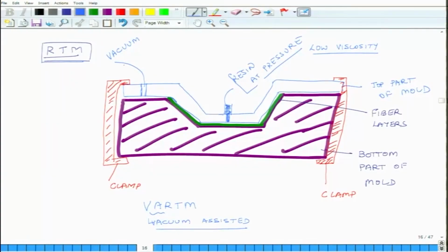You only rely on vacuum to draw the resin, and as a consequence, the orientation of the fibers is even better. But then you have to make sure that the viscosity of the fluid is extra low, so that it flows nicely and smoothly and it wets everything. So, this is resin transfer molding.